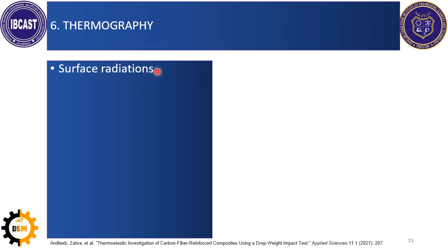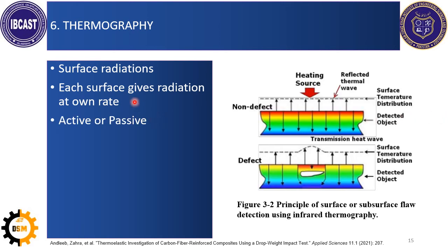Thermography uses the surface radiations with the help of a thermal camera. Every surface, when it absorbs heat, re-emits it in the form of infrared radiation. These radiations, with their rate and intensity, give information about that surface. Thermography can be active or passive, and the example shown here is active thermography, in which we give heat from an external source and then see its effect using the thermal camera. If you don't give the heat and you are naturally watching the thermal image, this is known as passive thermography. In this case, you can see that when there is a defect, there is a different amount of radiation emitted from the surface.